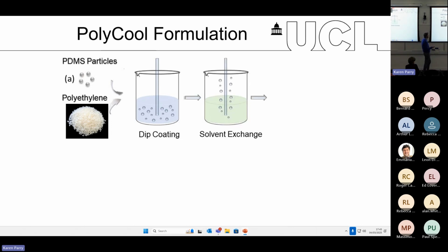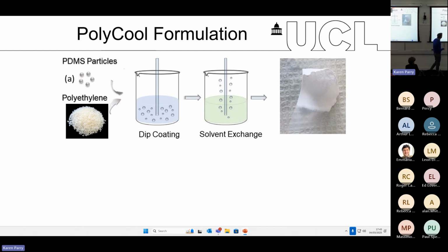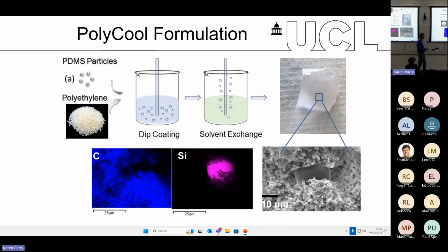We dip coated a substrate, and then we did a solvent exchange and a phase separation. And what came out of this is this porous material. The porous matrix is made of polyethylene, whereas inside we have the PDMS particles. And this is an EDAX, basically confirming the silicon content of the PDMS particles, whereas it's surrounded by a carbon content from the polyethylene.